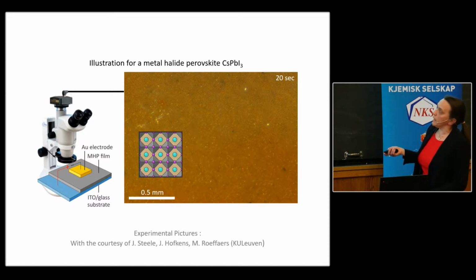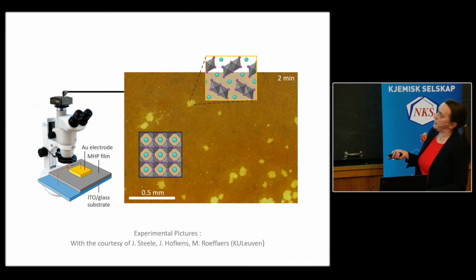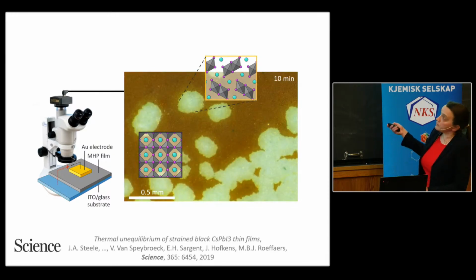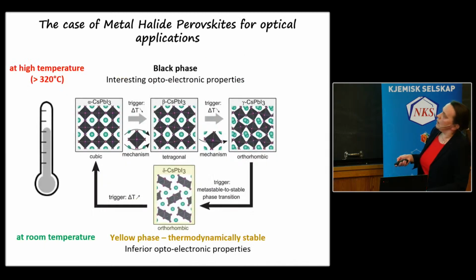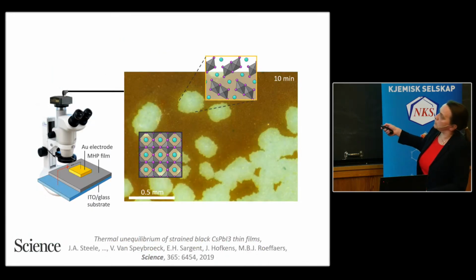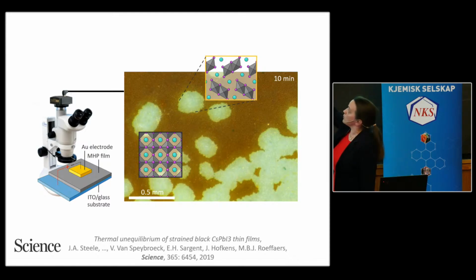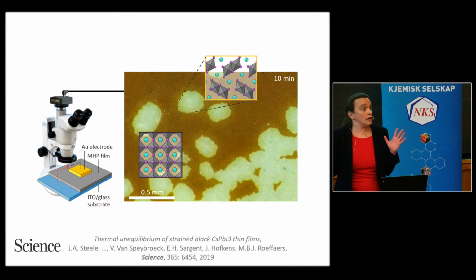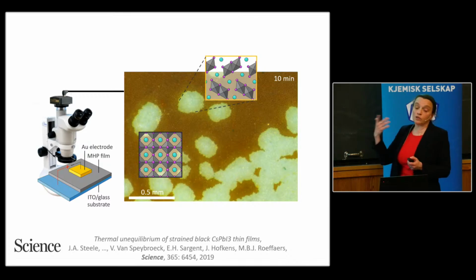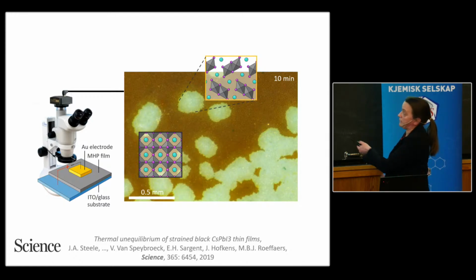Then when we expose that to room temperature, what you immediately see is that these yellow spots appear here. The material starts to degrade into something else we do not want. If you look at the atomic scale, this material transforms into another phase, and with time it goes very quickly. We can see all these big spots. The material that we now receive is not interesting anymore for optoelectronic applications. So, of course, we try to find methods to stabilize this phase.